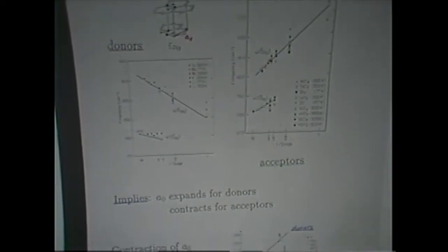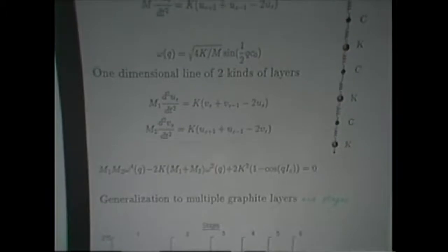And we show that the lattice constant for acceptors and donors behaved in an opposite way. And the different magnitudes have to do with the different amounts of charge transfer. This phononic problem was a lot of fun, really, because it provided some nice problem sets for solid-state physics. And I notice a number of people in the audience from my solid-state physics class, and you're familiar with these equations for coupled phonons in a solid one-dimensional line, the top being for similar species, and the second set of equations for two species on the line.